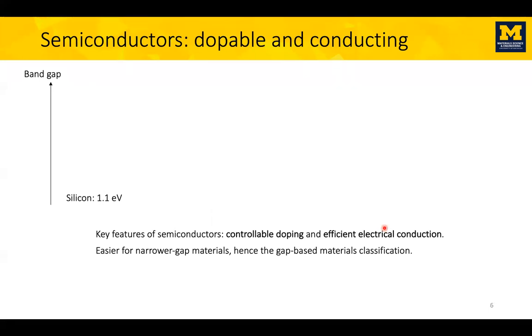They can be doped p-type, they can be doped n-type, and you can make things like p-n junctions or p-n-p transistors, which are actually smart electronic circuits. A diode conducts only one way. A metal cannot do that. And so the conduction of electricity is controllable by doping or by applying electric fields, and it is efficient. These two properties, doping and ease of conduction, are easier to achieve if your material gap is narrower. And that's where the classification comes from, based on the band gap.